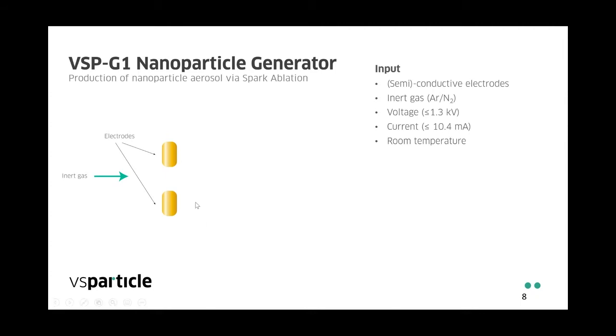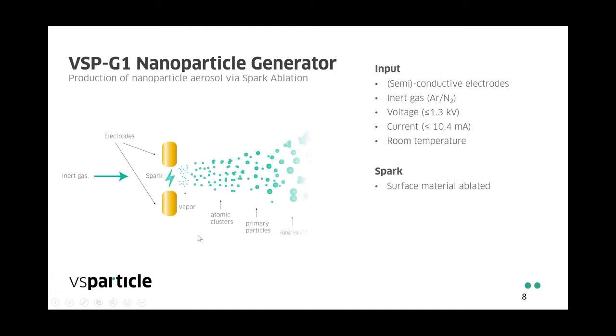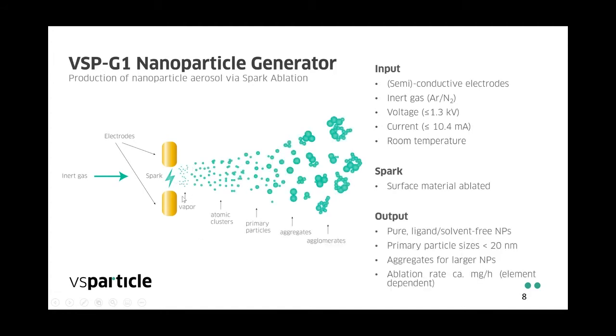Once we apply a voltage between the two electrodes, we get a spark, and this spark ablates or evaporates a small amount of the surface atoms on the two electrodes. What you get is a vapor of your electrode material, and this gradually sinters towards atomic clusters and then larger particles. These larger primary particles can then aggregate or agglomerate to form even larger particles. Overall, your output is pure ligand-free nanoparticles with a primary particle size below 20 nanometers, and we're able to obtain larger nanoparticles by aggregating these primary particles.